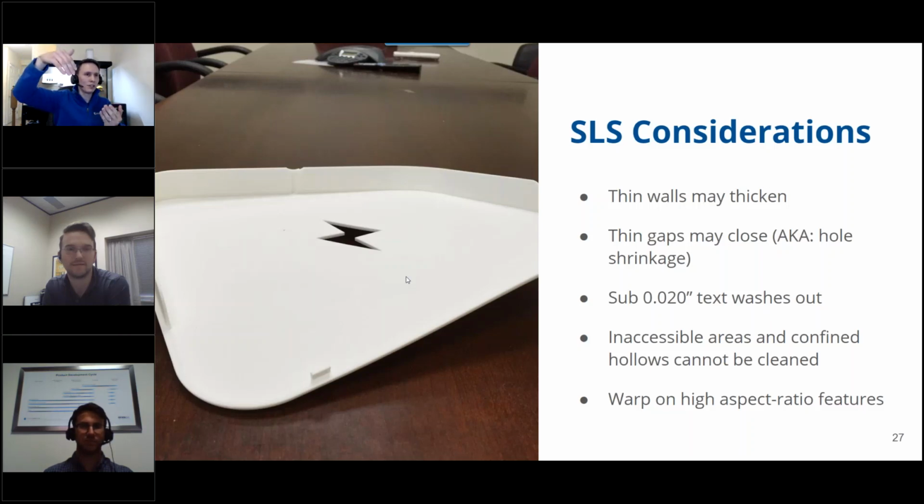So as that part fully cools after the build, it actually may get a twist or a warp or a curl. The way that you work through this is a lot of times you design around it. Sometimes it's working with a glass fill or an infill material that helps stabilize it, and sometimes it just may not be the right process for those types of longer parts, especially if it's like a big lid. Like FDM, it literally bolts the part down to the table when you're building it. Very good for those types of processes.